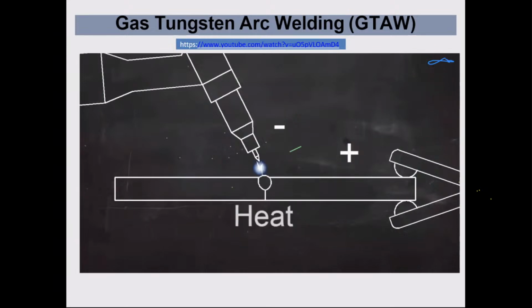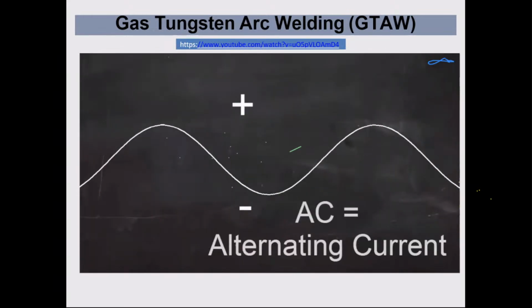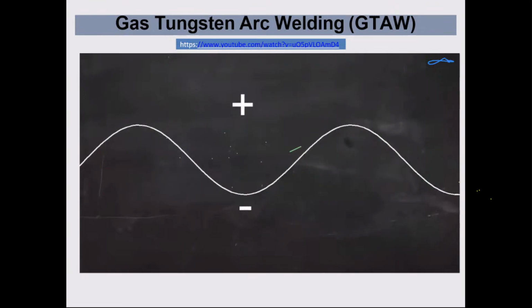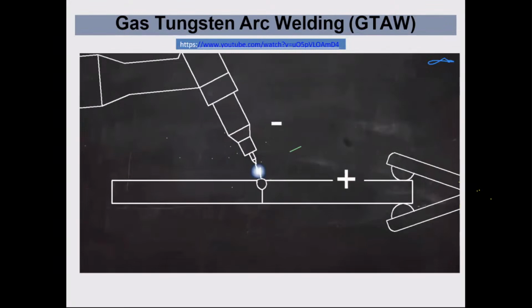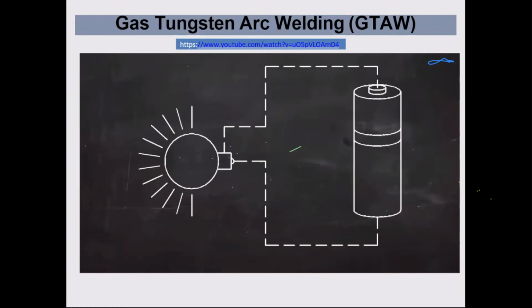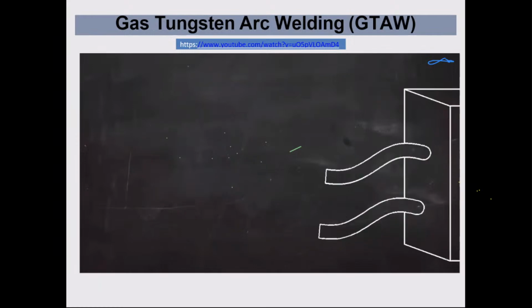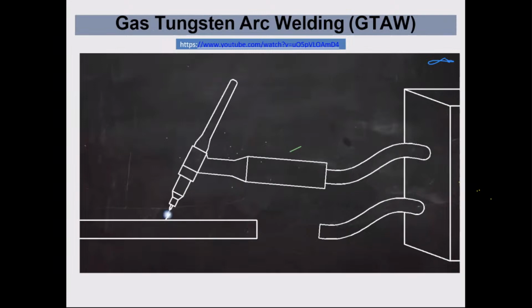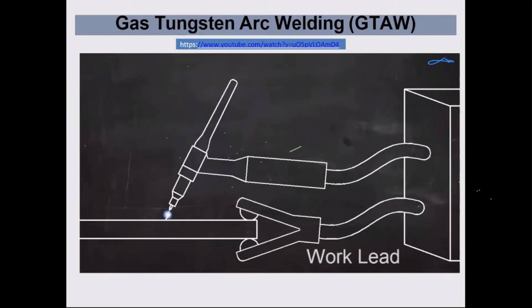DCEN puts most of the heat on the workpiece, and it's the most common setup. When welding aluminum, however, AC is used. In AC, the positive and negative voltages switch back and forth between the electrode and the workpiece. And this puts more heat on the electrode, but it has a cleaning effect on the workpiece. You see, aluminum forms oxides that float to the top of the weld pool and prevent a good weld. AC current helps control these oxides. In an electric circuit, the current flows in a loop. In TIG welding, the current has to flow in a complete circle from the machine to the torch, into the work, and back to the machine. A work lead is clamped to the work to complete the circuit from the workpiece back to the machine.